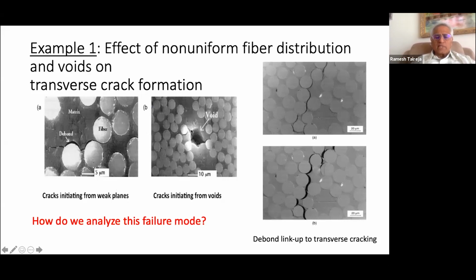Here's another example which I showed earlier, where defect is playing a major role. So voids is one type of defect, and non-uniform distribution of fibers, that is to say clustered fibers and resin-rich pockets, those are sort of the features of the internal structure that in this case are important.